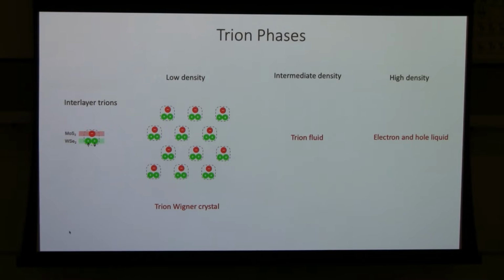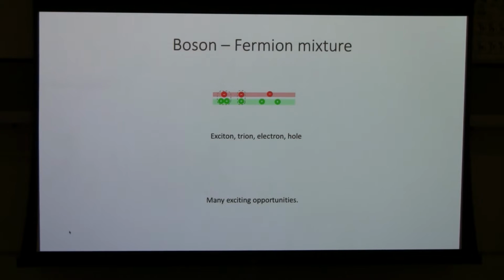But if you go to even higher density, then the electrons and holes can screen the interactions and you go to an electron-hole Fermi liquid. So it will be quite interesting to see how the different phases evolve when you vary this trion density. Of course, you don't have to fix the electron-hole density ratio to be just 1:1 or 1:2. You can continuously vary the density ratio.